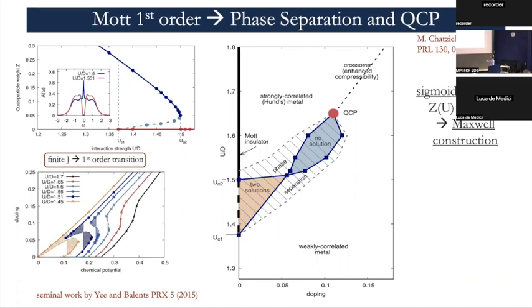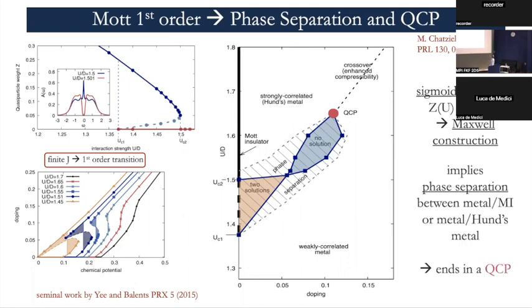Actually, you can do a Maxwell construction here, and you will find this zone of phase separation. And when the line straightens at this point, you have a quantum critical point with infinite compressibility, which actually emerges out of the phase separation zone. So this is a generic phase diagram in which what you will maybe be able to see experimentally is this part, this quantum critical point, this transition abruptly with a zone of prohibited doping between two different kinds of metals. And in the part which is beyond the quantum critical point, you will get a crossover, in which you will have an enhancement, not a divergence, of the electronic compressibility.